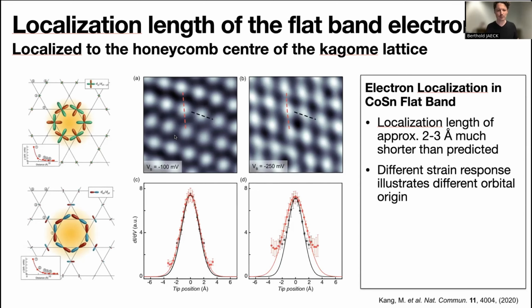Now, what we find when we essentially take line cuts along these maps and analyze the amplitude decay of the dI/dV signal, we find that the localization length is much shorter. As a matter of fact, the electronic states are localized at length scales of perhaps 2 to 3 angstroms, which you can see is almost half the value of what people predicted from DFT calculation. So I wouldn't necessarily say that DFT calculations are wrong here, but perhaps they're not accurate enough to actually account for all the extra correlation effects that may appear in these d-orbital derived electronic states.